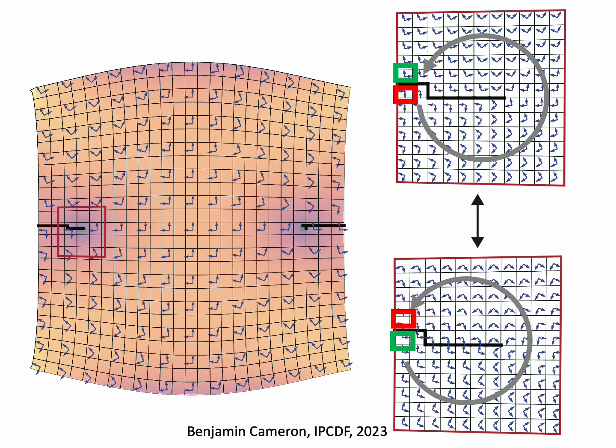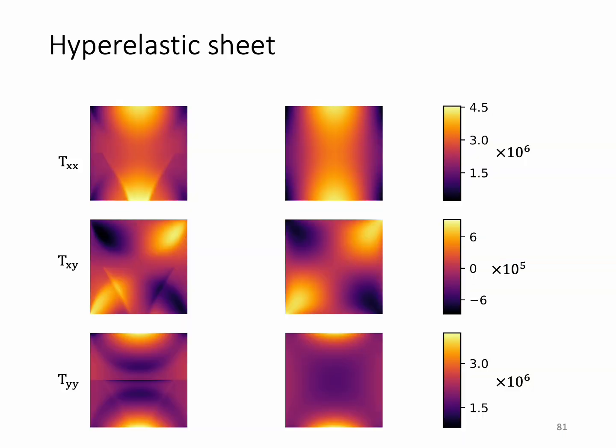And we can just apply this with the finite volume method to solve the equations. On the left is the stress field calculated with this approach. On the right is the stress field solved from the finite element computation. You can see that there is reasonable agreement, although there's a bit more error than some of the previous examples I've shown you. That's because of the high curvature of the characteristic lines. And we're actually in the process of running simulations on finer and finer grids, and we're confident it will converge to essentially the exact solution in the same way.